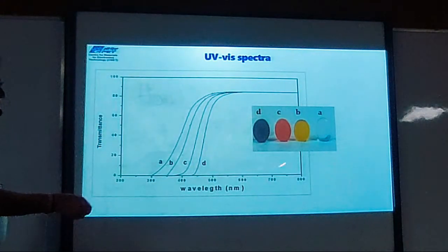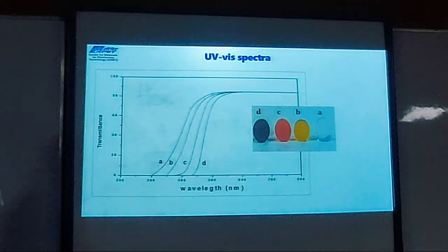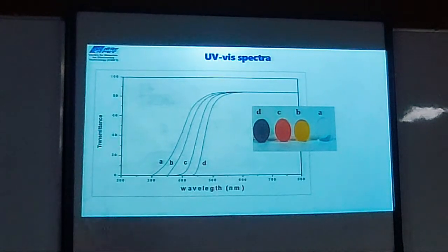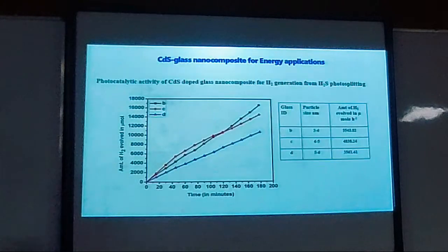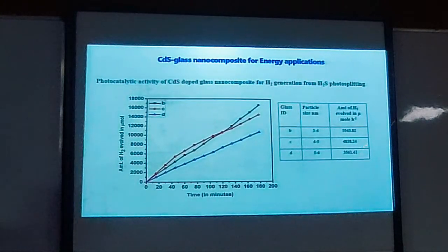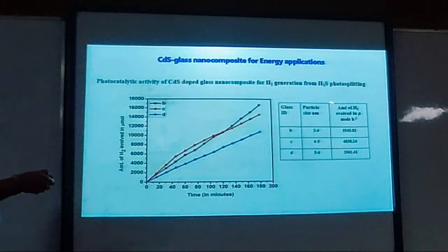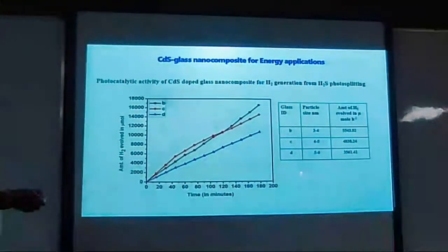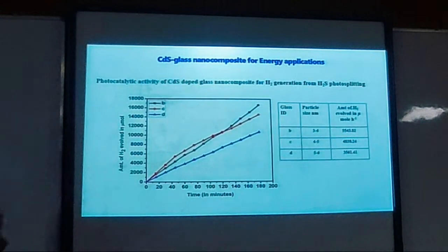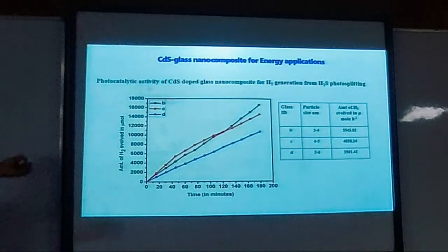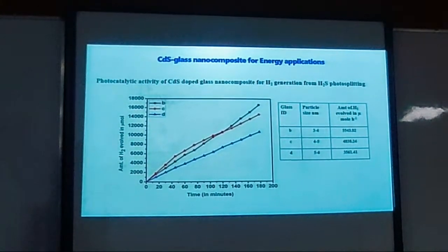Considering this, we thought whether this can be utilized for hydrogen production for the first time. So we have taken a US patent on this for hydrogen production. This is a cadmium sulfide quantum dot glass. You can see the particle size is 3 to 4 nanometers here, which gives a much higher hydrogen evolution, 5543, from the sample we use here, 0.5 gram of glass, which contains hardly 0.005 grams of cadmium sulfide.